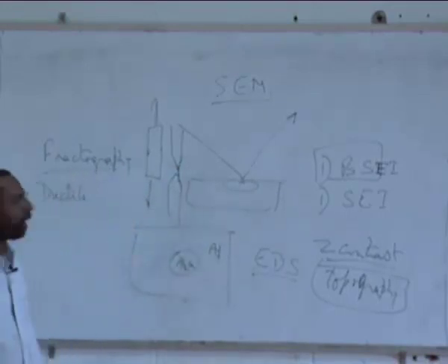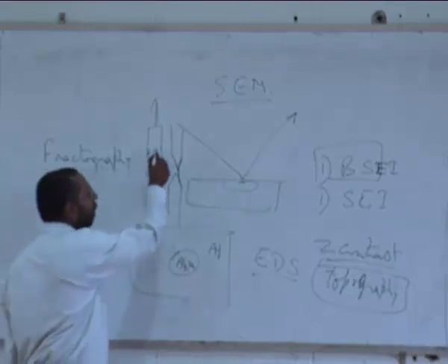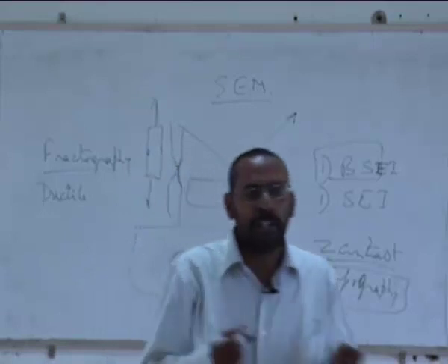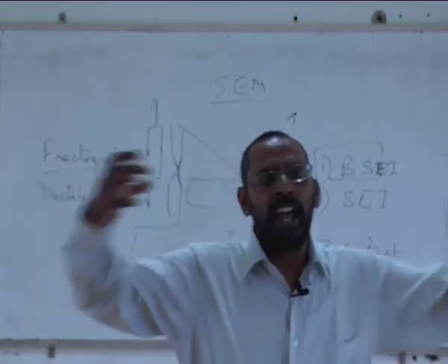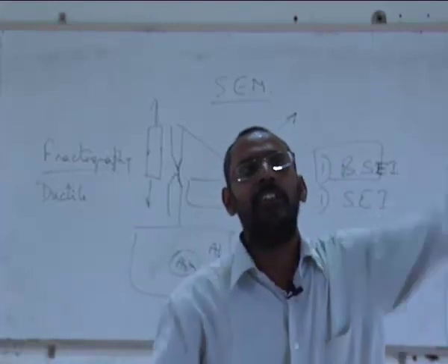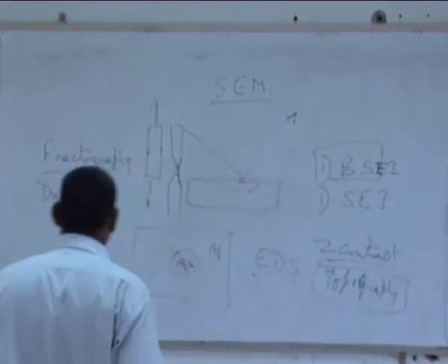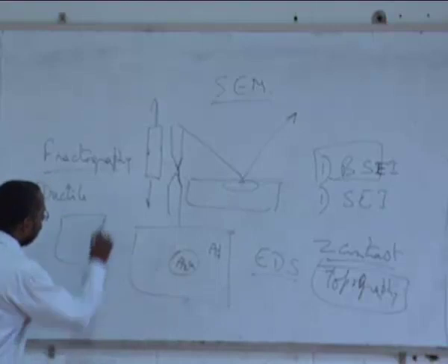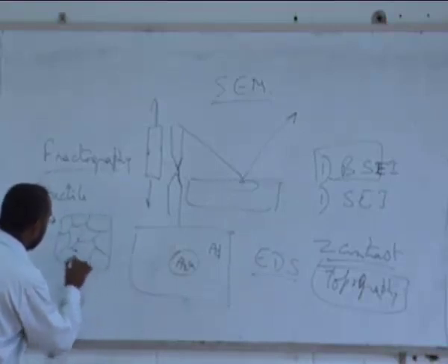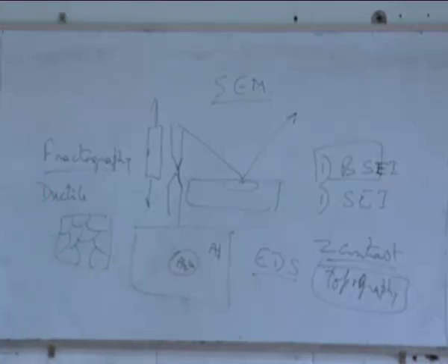This cup and cone fracture comes because there are a lot of voids generated inside the material. Whenever there is a small crack inside, all these cracks come together, and then the cracks get joined together, and finally the fracture takes place. And these voids will look like equiaxed dimples.